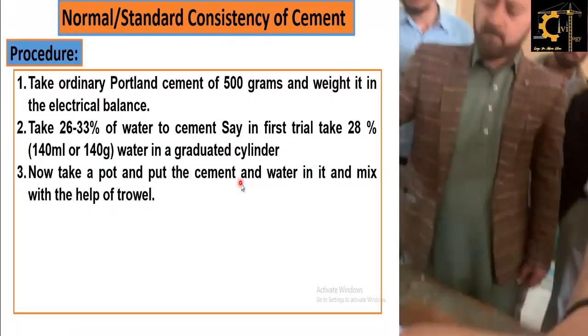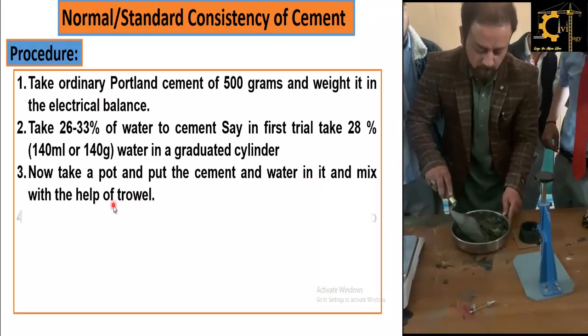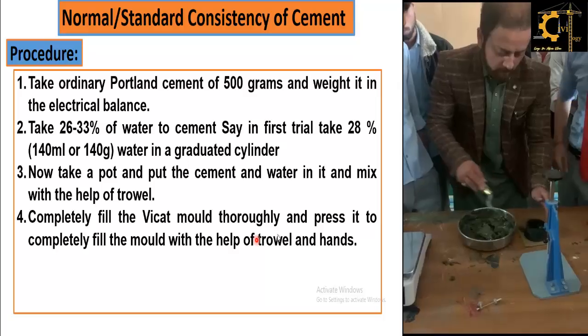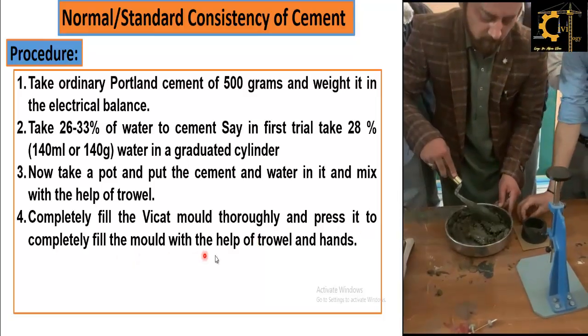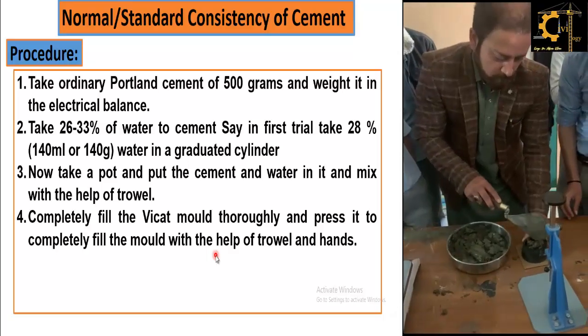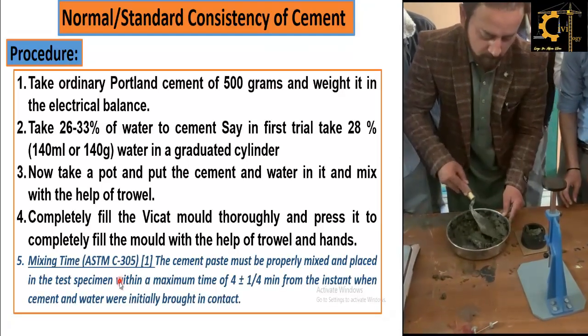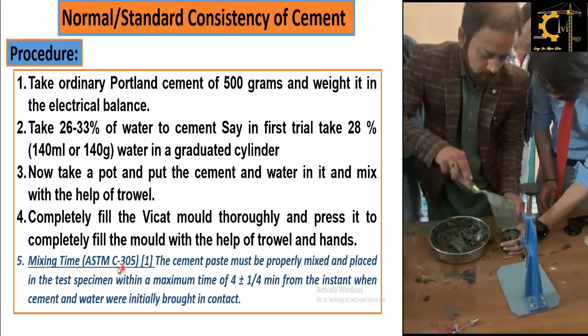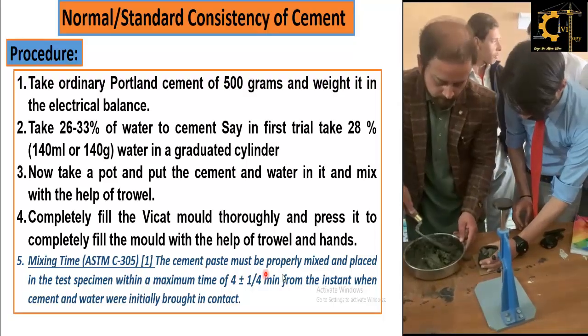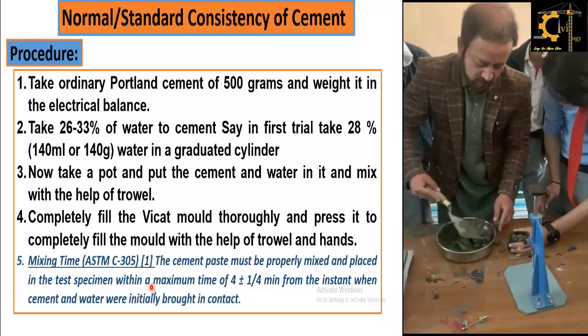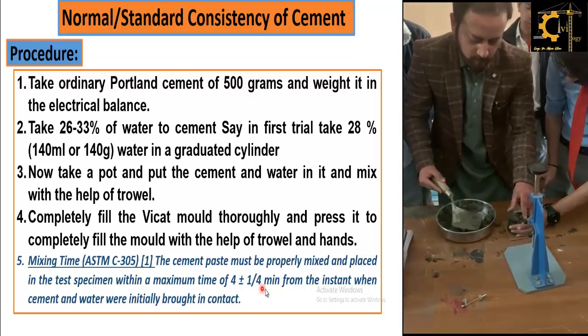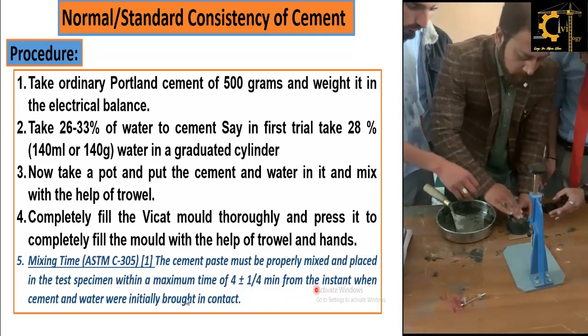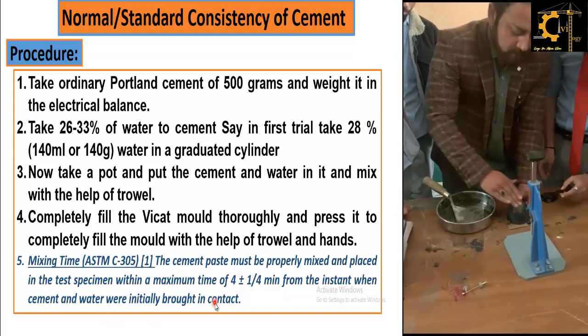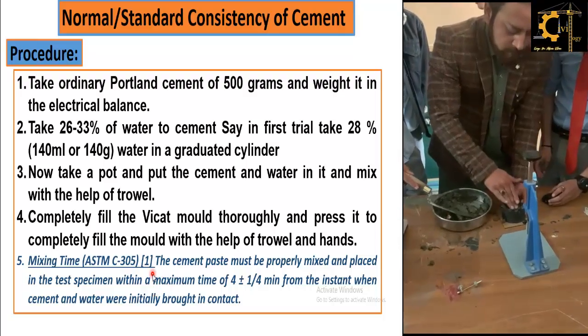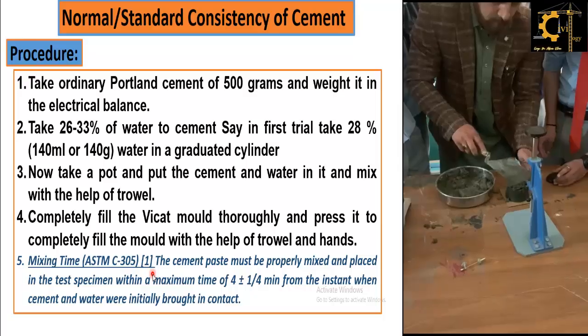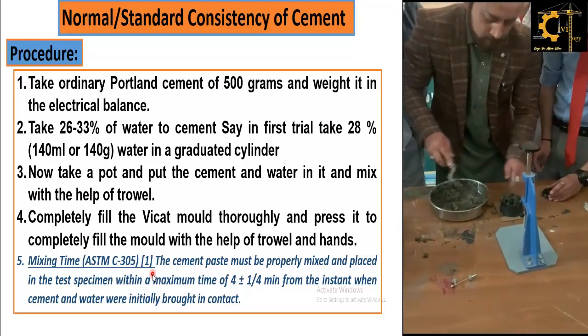Now take a pot, put the cement and water in it and mix with the help of a trowel. Now completely fill the Vicat mold thoroughly and press it to completely fill the mold with the help of a trowel or with the help of hands. Now it is very necessary to note down the mixing time. According to ASTM C305, the cement paste must be properly mixed and placed in the test specimen within a maximum time of 4 plus minus 1/4 minutes, or you can say 4 minutes, from the instant when the cement and water were initially brought in contact. This time should be noted when cement and water come in contact, and a stopwatch should be started at that time.